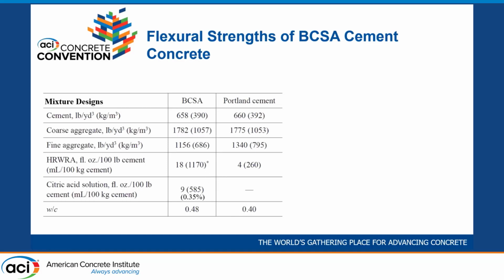And as I mentioned before, we just tend to use high range so that we can get it into the forms quickly, where it can self-consolidate a little bit, so we're not spending a bunch of time getting it consolidated into the forms. And we used a 0.35% citric acid dosage here. This is expressed in terms of this solution of citric acid that we make, that we use in 9 fluid ounces.